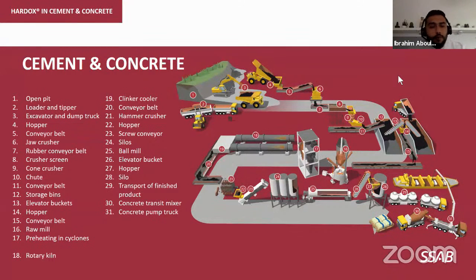Moving forward again to point number 25. Okay, we did some elevator buckets and screw conveyors after the hammer crusher did the crushing. Now we need again to do some grinding. For that, we go to step number 25, in which we have the ball mill, which is a cylindrical tube that rotates all the time. It has some liners that can be made from Hardox grades 500 to 600 embedded into rubber. And there are some steel balls that rotate with the ball mill in order to grind the material.